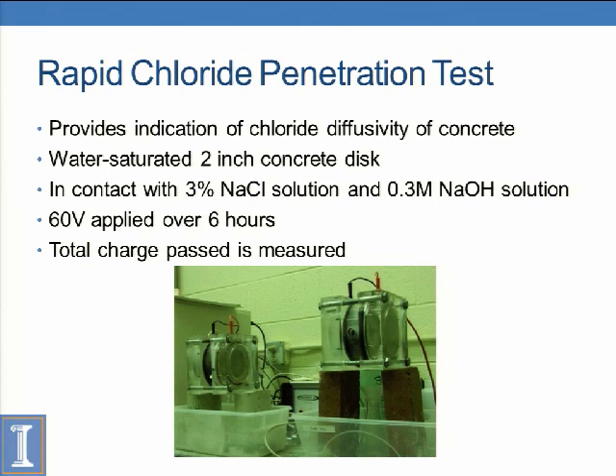So rapid chloride penetration test pretty much is a test that we use to give us an idea of the permeability or diffusivity of the concrete. So if you have very interconnected pores in your concrete, you'll have high penetrability of chloride ions. So with this test, you have a 2-inch thick concrete disc. On one side you have a sodium chloride salt solution. On the other side you have sodium hydroxide. And then you apply a voltage across the two cells, and you'll drive the chloride ions through.